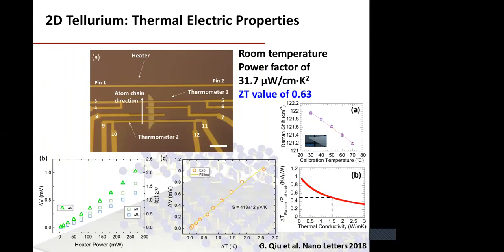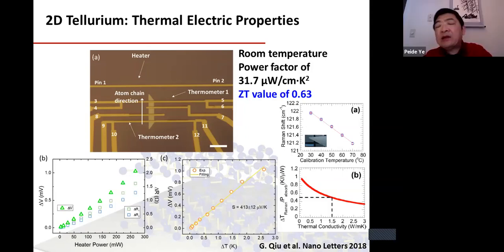By the way, I have a question for the material part. For tellurium, did you check maybe with XPS or EDX to show it's really 100% made of tellurium, meaning there are no other atoms bonded? Yes, I did. In the middle part it is tellurium for sure, but there is some, let's say, sub-nanometer layer, where by XPS you can see there is tellurium dioxide. So very, very thin, it's possible it exists. But it's not another element, depending on your accuracy, the resolution. It's mostly true. I don't have the number, let's say how many nines. But we can see mostly it's true, 99.9% probably is true.